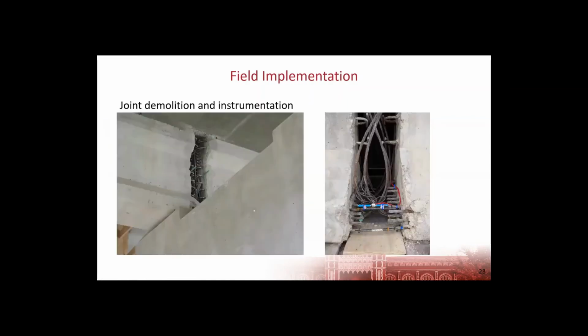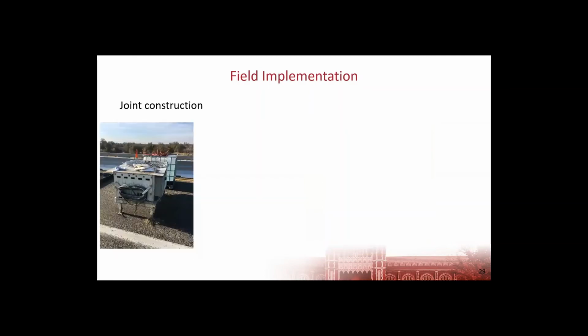Then the joints were demoed by the contractor doing the rehabilitation on this bridge. We installed some strain gauges in an exterior joint and an interior joint between spans 3 and 4 so that we could look at deformations after repair that we couldn't look at in the pre-repair load test. Then the joints were constructed using the proprietary UHPC, Ductal.